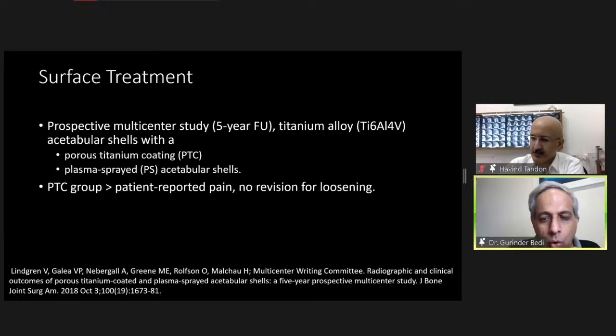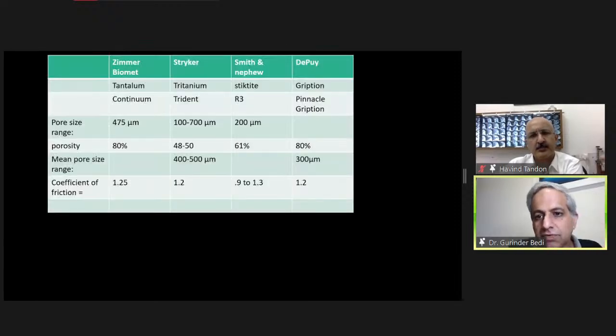So the issue is, which coating works best? The answer is there are two types. One is a porous one and one is a plasma sprayed one. So the PTC, which is a porous titanium coating, is the one which works the best. Basically, it's a sintering process which they do. So the particles, or the roughness, actually sticks to it much, much better, and debonding does not happen.